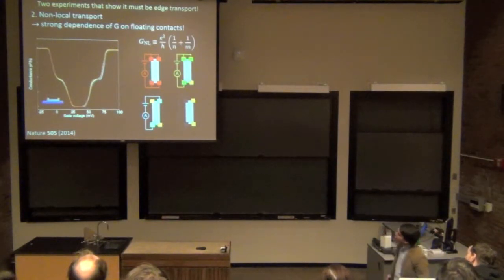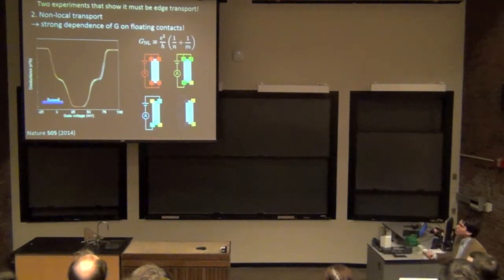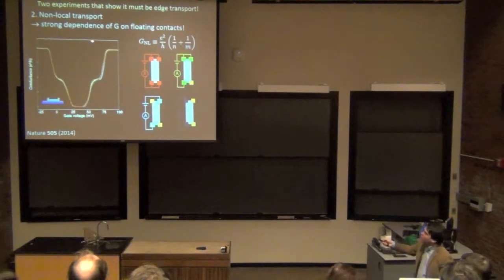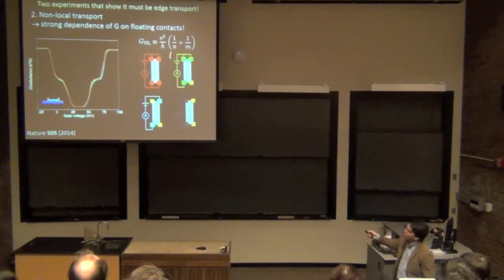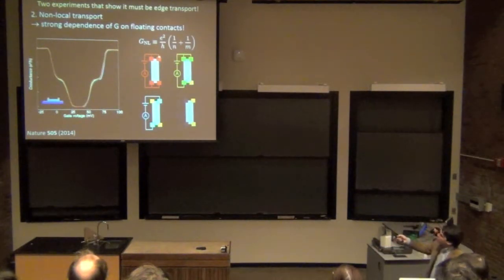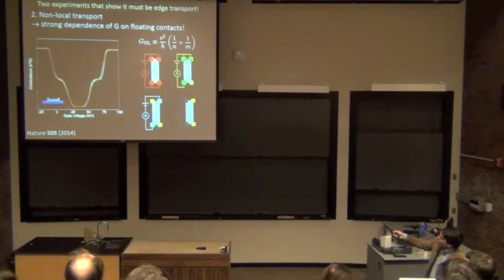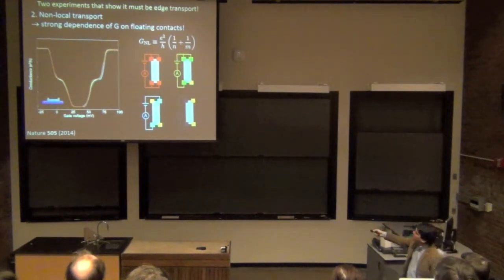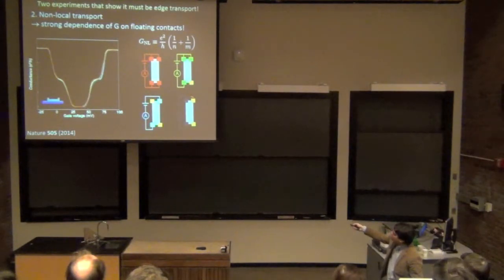And then the second experiment that we did to show that it has to be transport along the edges goes under the name of non-local transport. So what we're doing here is we have a sample with four contacts on it. We're measuring the effect of two-terminal conduction in each of these configurations. Here we're measuring transport from here to here along two edges. Here we're measuring transport from here to here along one edge in parallel with two edges. Here one in parallel with three edges, and here two edges in parallel with two edges.